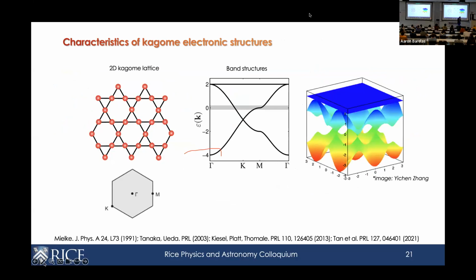Let me just make the following couple key points. If you take any Kagome lattice and you look at its band structure, there are 3 important signatures that are always there in this band structure. So let me illustrate that. I keep pointing at this. Maybe some of us are not so used to looking at this. You can imagine this is your real space. If you cut your crystal down and you really look at it with a very fine microscope, eventually you will see this in real space, right? But band structure lives in momentum space, and this is the repeating unit in momentum space, which is the Brillouin zone. So the way we represent this is by drawing the band dispersions on a pathway. So this is gamma point to K point to M point back to gamma, right? So this shows you there are 3 bands, and you can see how they go around, right?